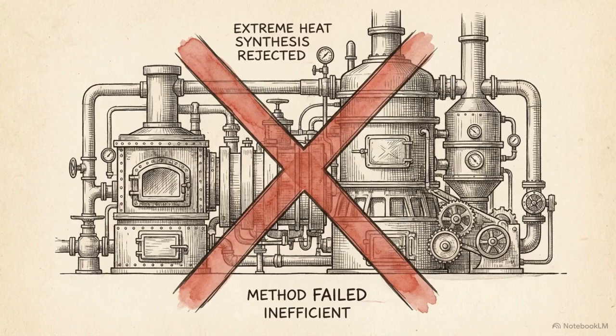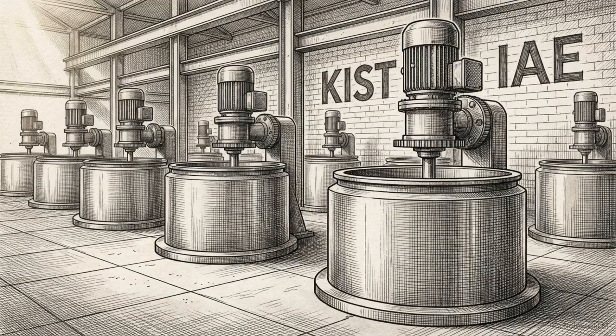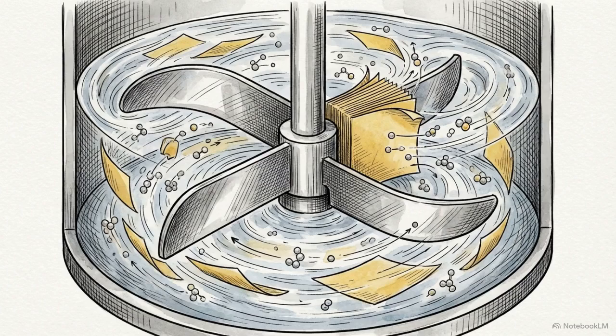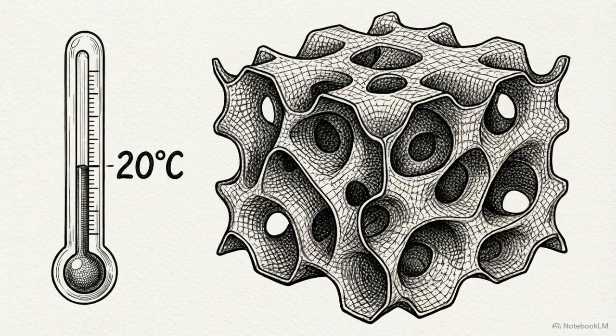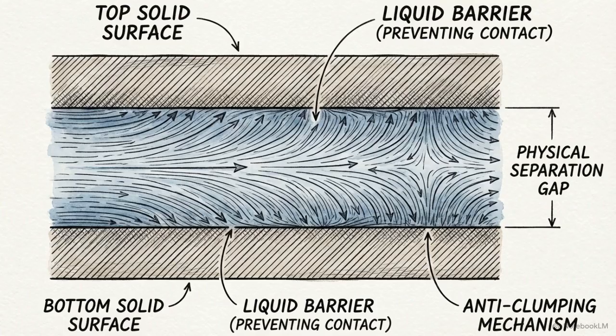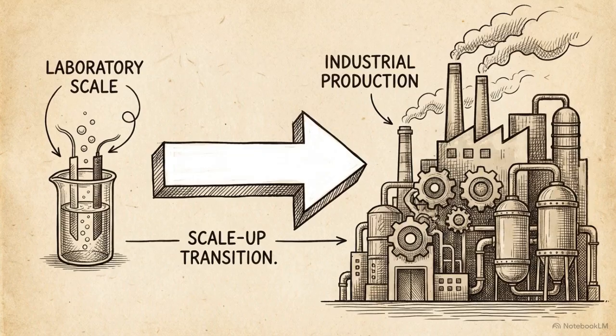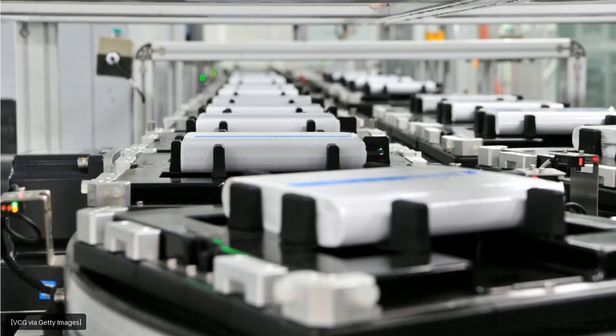To bypass the need for vapor deposition and intense heat, researchers at the Korea Institute of Science and Technology and the Institute for Advanced Engineering developed a room temperature stirring method. By processing the materials using standard industrial shear exfoliation mixing, both the platinum substitution and the selenium vacancy formation occur spontaneously under ambient conditions. Operating at room temperature preserves the structural integrity of the material. It actively prevents agglomeration, ensuring the nanosheets remain laterally extended with their active surface area fully exposed. Eliminating high-heat vacuum furnaces in favor of scalable, room temperature mixing allows us to transition this technology out of scientific isolation and into a mass-manufactured commercial product.